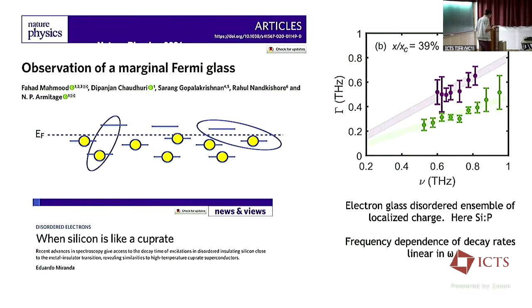And I always found one of these early papers of Phil Anderson on the disordered Fermi glasses very inspiring. And this idea of some universal state of matter of disordered fermions called a Fermi glass, we made kind of homage to that original idea. The linear in frequency dependence with a coefficient close to 1 is very similar to various things that have been discussed in the context of marginal Fermi liquid. So we called this state of matter the marginal Fermi glass, and were able to learn about that, again, through doing 2D coherent spectroscopy. Okay, so those are some of the things that we were doing.